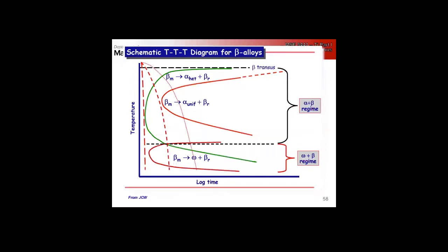And so we can see, this is just the kinetics, right? So heterogeneous nucleation versus uniform nucleation. If we have enough alpha potential nucleation sites, we can come down through and we can miss the curve of this. If we don't have enough heterogeneous nucleation sites, we're going to come down, and if we miss the nose here, we're going to come down into the omega region. So if you have enough alpha sites, you'll have the